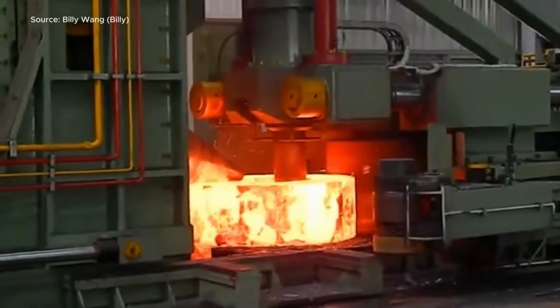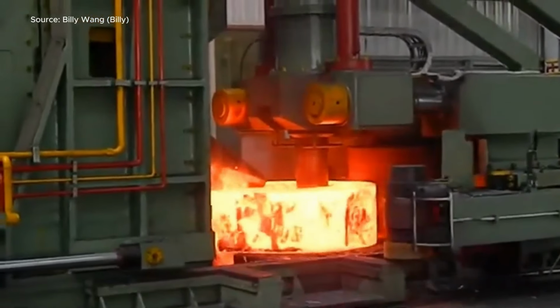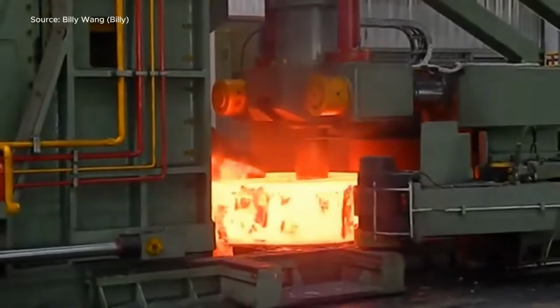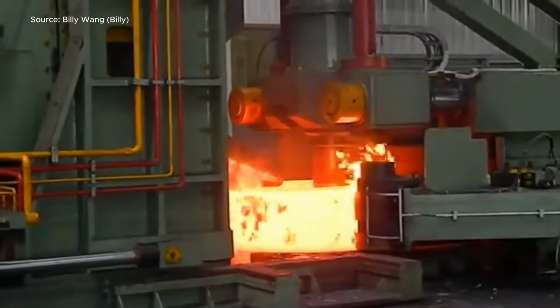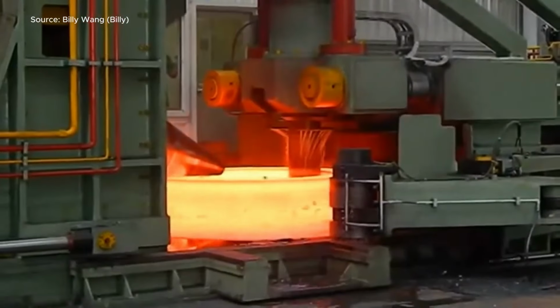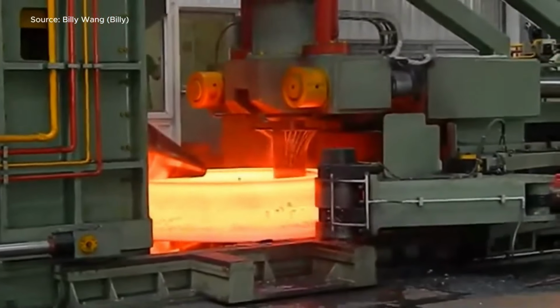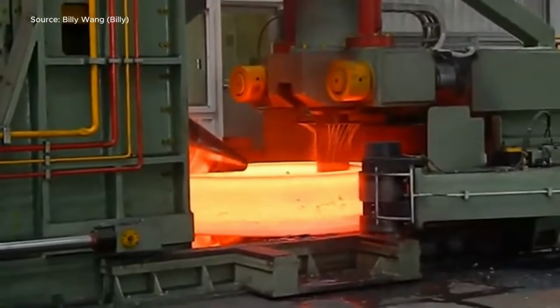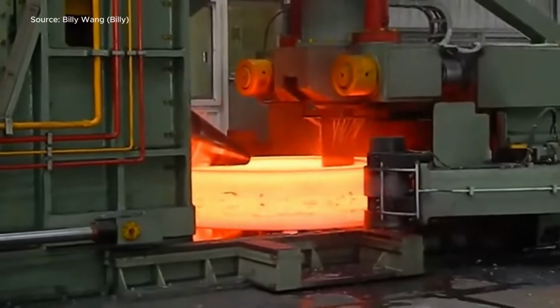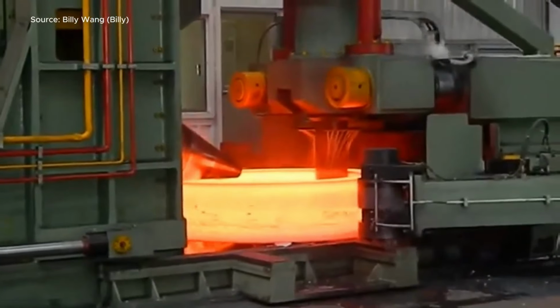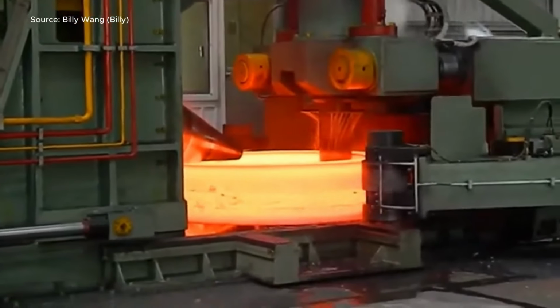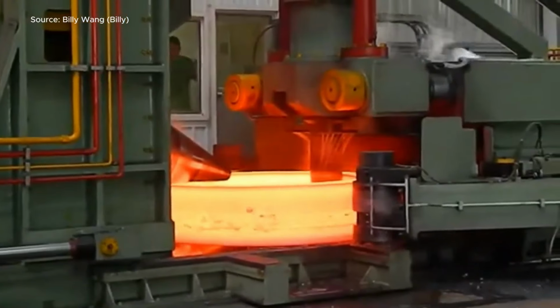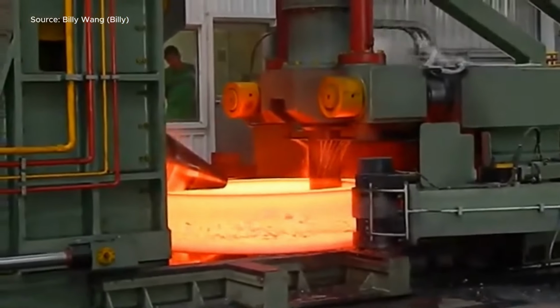The D53K series ring rolling machine operates through a combination of radial and axial rolling processes to form seamless ring forgings with high precision and efficiency. The process begins by heating a pre-formed billet, typically made from carbon steel, alloy steel, or other metals, in an induction furnace to a temperature between 1,100 degrees Celsius and 1,250 degrees Celsius.